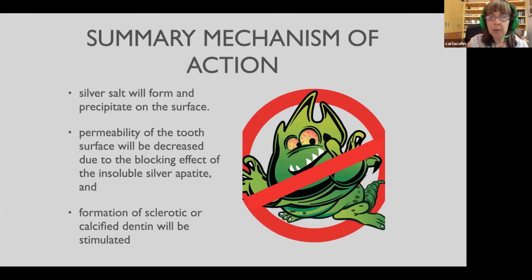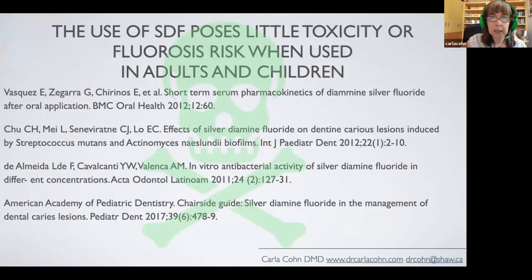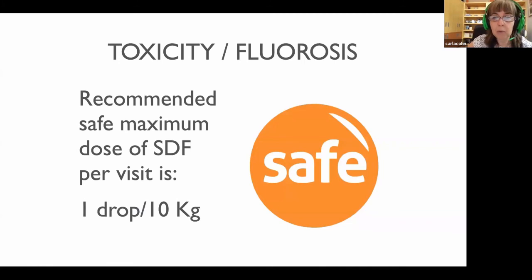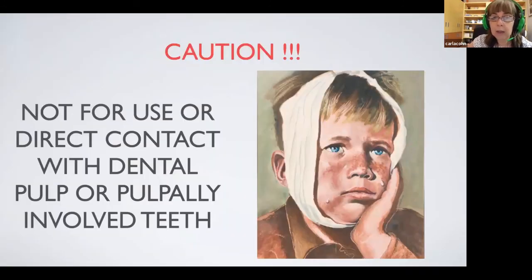So the summary of the mechanism of action is the production of a silver salt forms a precipitate on the surface of the tooth. The permeability of the tooth surface will be decreased due to that blocking effect of insoluble silver apatite, and formation of sclerotic and calcified dentin will be stimulated. Use of silver diamine fluoride poses little toxicity or fluorosis risk when used in adults and children. We have a maximum recommended safe dose of 1 drop per 10 kilogram patient. Very important to know that silver diamine fluoride, Riva Star, is not to be used in direct contact with the dental pulp or pulpally involved teeth. So a tooth that has a pulpitis that you think is going to have communication with the dental pulpal complex, we do not want to use this medicament on there.